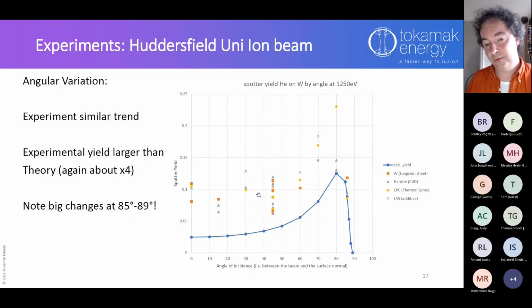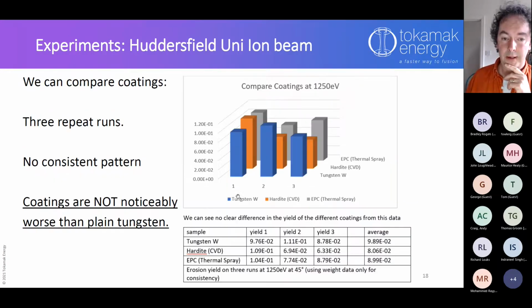This was a sort of second set of experiments we did, and we refined the technique a little bit by this point. In my opinion, you can definitely say this is following this sort of trend. It rises up and then it's dropping down at the end there. The experimental results are higher, so there is more sputtering happening than I predicted, but we're within a factor of 4. That isn't so bad. Not bad for a first go.